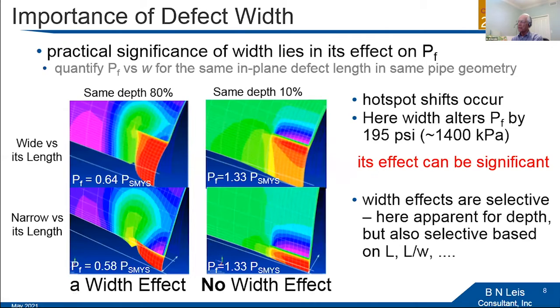Importantly as well, if you look here, the highest stress occurs in the middle of the defect, whereas for this feature, it occurs near the edge of the defect. So the hot spot for corrosion is shifting, and that has implications for detection and sizing. It has a significant effect. Here, the width effect is a function of depth, but the width influence is selective in regard to the length. It's selective in regard to the aspect ratio, that is to say the length to the width, and other parameters.